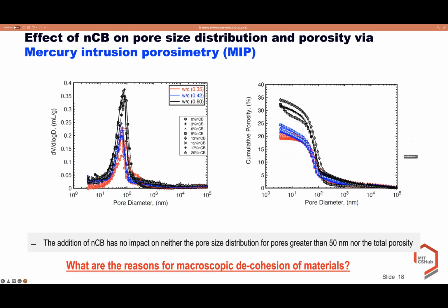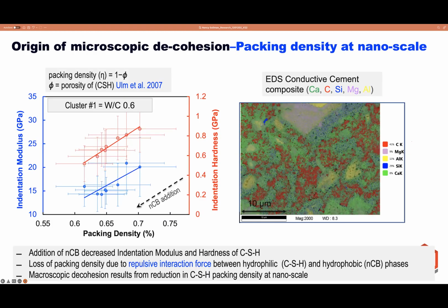Now we need to understand what is the reason for microscopic de-cohesion. This is why we are going to study the effect of nanocarbon black at nanoscale, where we show the effect of the packing density. This slide shows the packing density versus hardness on the left-hand side and the indentation modulus on the right-hand side. The packing density is a very important parameter as it represents the nanoscale porosity of low density CSH and high density CSH, the main constituents of the bonding agent.